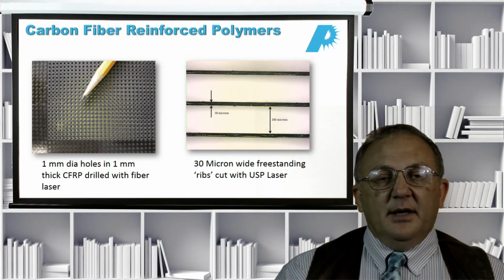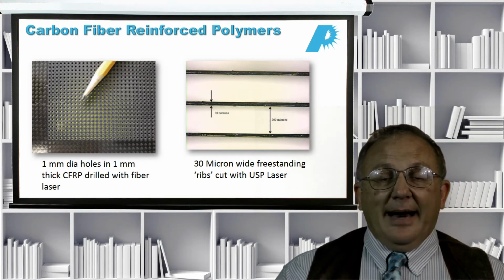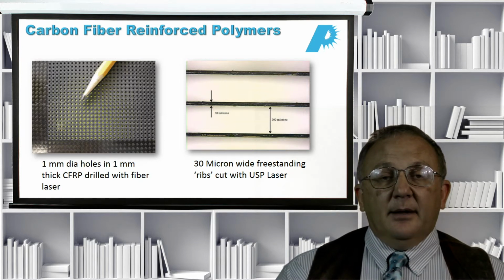On the left we see 1 millimeter diameter holes in 1 millimeter thick carbon fiber reinforced polymer, and that was drilled with a 1 micron fiber laser. On the right hand side you see 30 micron wide freestanding ribs, also cut out of the same material, but this time using an ultra short pulse laser. This is the 355 nanometer 10 picosecond pulse length laser, and these ribs were left standing and intact, and the rib width, like I said, is about 30 microns.